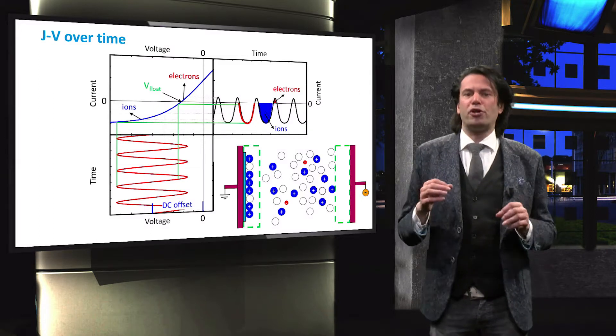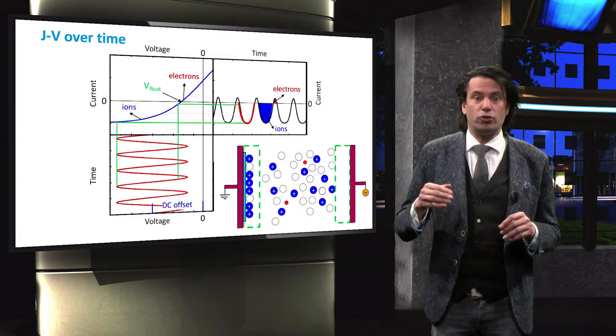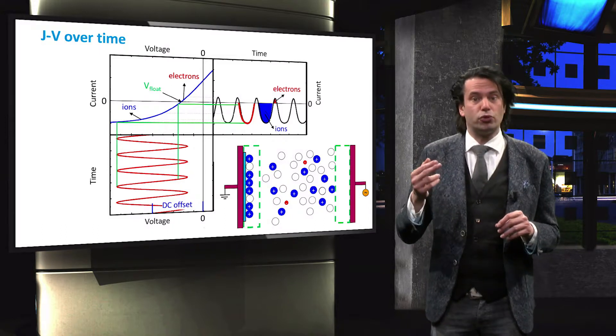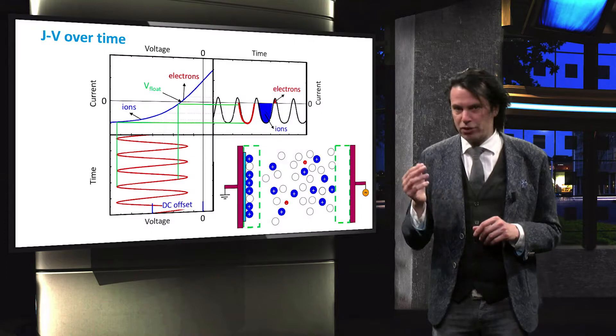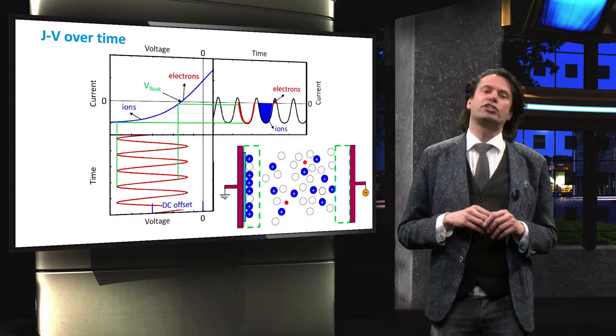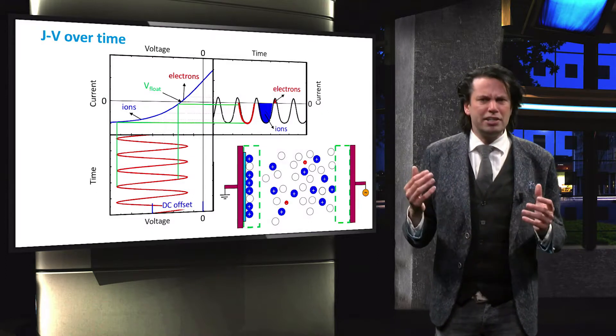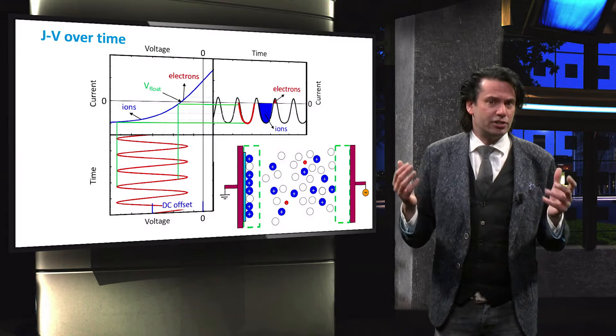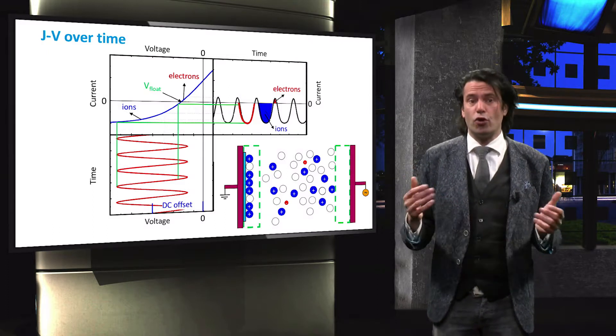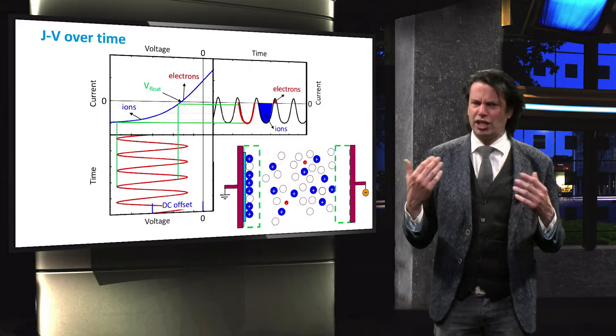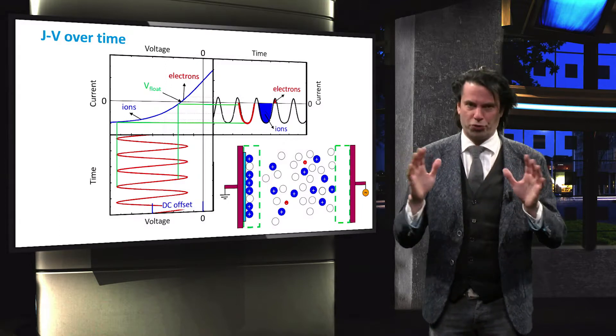During the point of the lowest potential in the cycle, the ions impact on the substrate surface with a high velocity. The impact of these high-velocity ions can damage the surface of the film, leading to defects in the grown material. As such, for the growth of a dense and stable film, the velocity of the ions needs to be moderated.